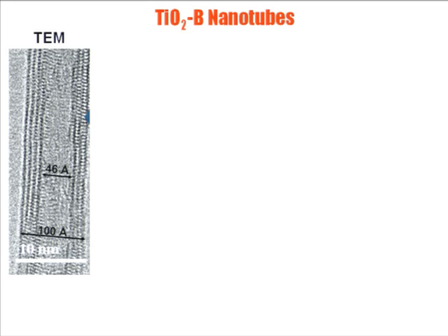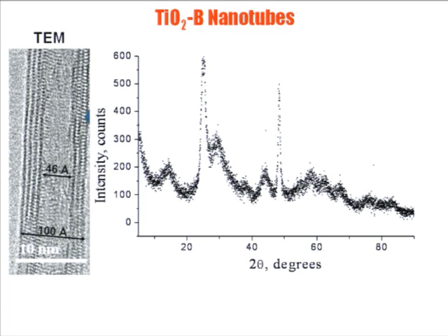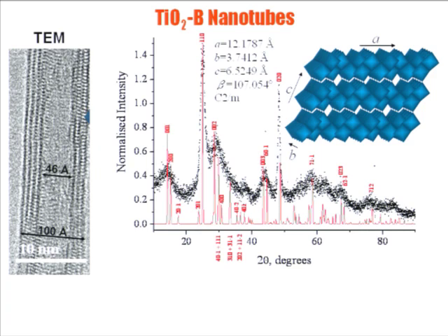And when we look at the diffraction pattern, it looks like this. Hardly the prettiest thing you've ever seen. But nevertheless, even at a glance, you can probably guess, and it would be a fair guess, that there is severe anisotropic broadening here. And this we can confirm if we superimpose the diffraction pattern calculated from the bulk structure. The bulk structure looks like this. I won't go into details, don't have time. So it's a monoclinic structure with these lattice parameters and space group C2/m.